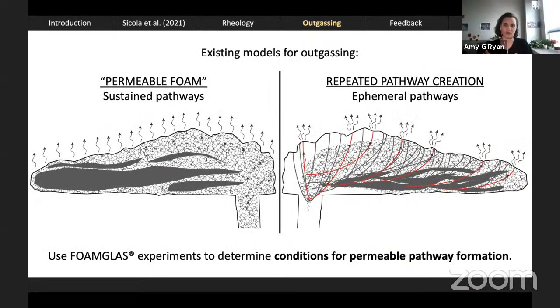There are two prevailing models for this physical understanding of outgassing. The conceptual model on the left is the so-called permeable foam model. In this model, the idea is that the bubbly melt is moving towards the surface. As bubbles are growing, they connect with one another, creating a high permeability material. And that high permeability is essentially sustained through the entire period of that lava flowing across the surface. This allows for continuous passive outgassing, and at some point at the flow front, because it's had so much time to outgas, all the volatile phase has been lost, and we're left with dense regions of bubble-free melt that are later quenched to obsidian. And this, as I said before, is something that we frequently observe in silicic lavas in the field.